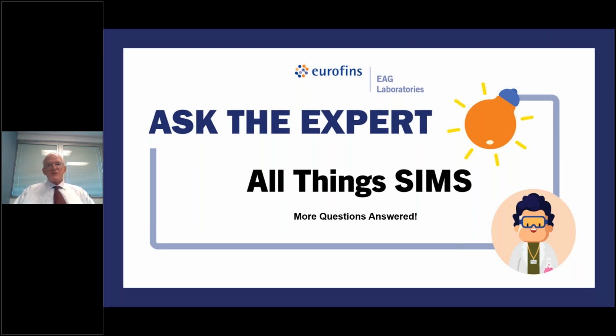EDS, a very powerful tool. It's used mostly for major element analysis, mapping, or line scans. It's not very often used for quantitative analysis because EDS really doesn't use standards. You use tables of sensitivities or relative sensitivities. But SIMS uses standards, so we can oftentimes be quite quantitative in these same kinds of samples.